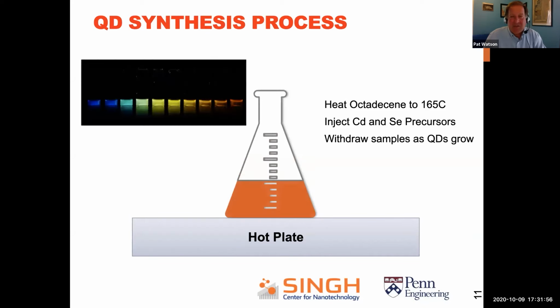Okay, and then with time we just withdraw samples. The longer it's in there, the larger these crystals will grow. So now we can get a whole variety of quantum dots. They're chemically identical. They just have different characteristic sizes. And here's a plot from a paper where we took some of the recipes. They can demonstrate all the way from this beautiful deep blue color to red using cadmium selenide, and you get all these colors of the spectrum. We've never been able to do that in practice. We can get parts of this, one part or the other, but we haven't been able to get it in one run. So we don't know how they did it exactly.